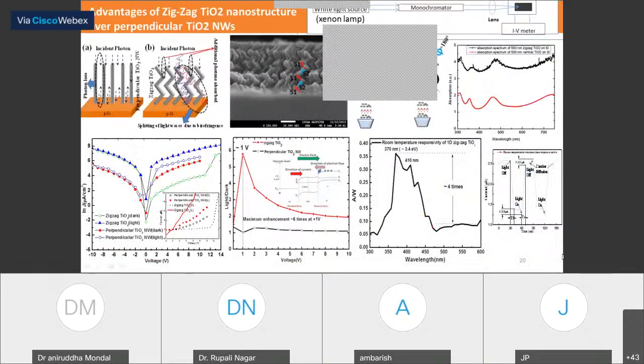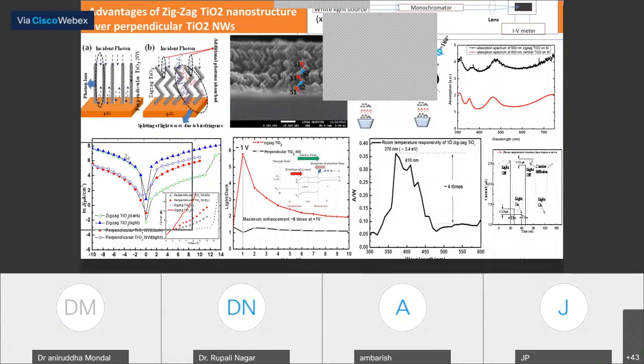Again, if you go for another kind of nanostructure, which has been shown here, we have fabricated two kinds of devices. One is based on zigzag nanowires. The zigzag nanowires have been grown this way. Once we have deposited at phi equal to 0 degrees, then we rotate to phi equal to 180 degrees, and then the deposition is made. So we get one structure in the right-hand direction and then the left-hand direction. So this is the zigzag structure.